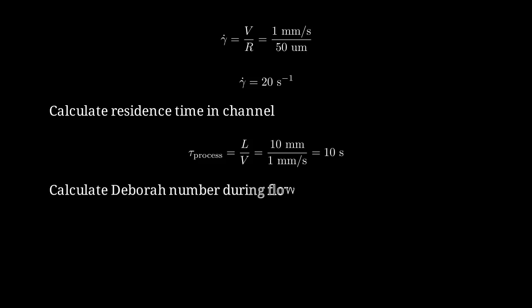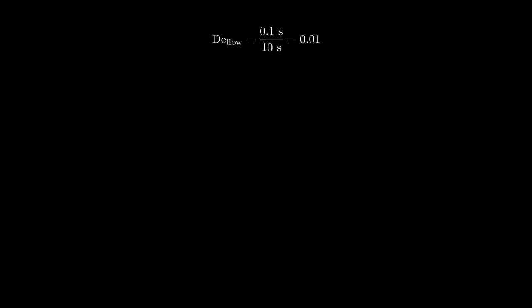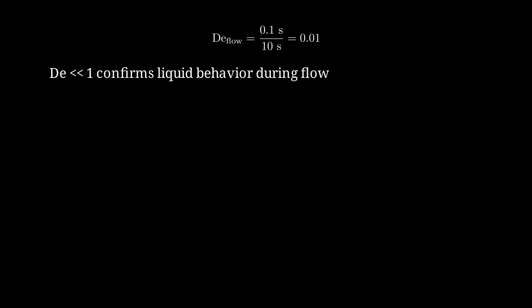Now we can calculate the Deborah number during flow. De during flow equals 0.1 divided by 10, which is 0.01. This is much less than 1. Since the Deborah number is much less than 1, the material behaves as a liquid during flow, exactly as we expected. After the droplet exits, the shear stops almost instantaneously. The relevant time scale becomes the relaxation time. The Deborah number after exit effectively approaches infinity because the process time drops to nearly zero while the relaxation time stays at 0.1 seconds. The result is rapid gelation or solidification.